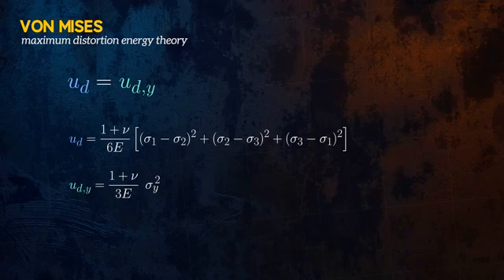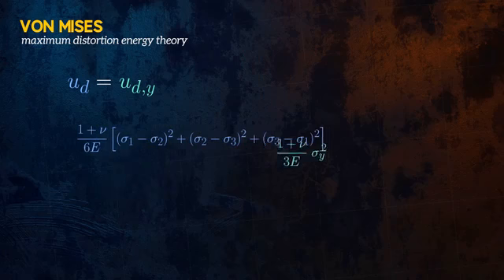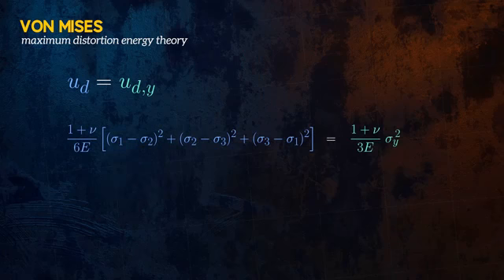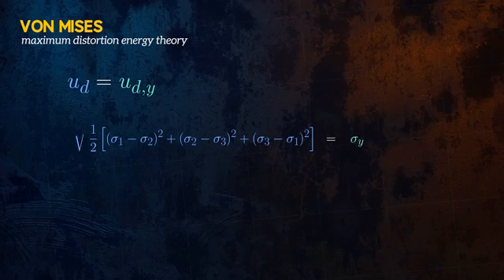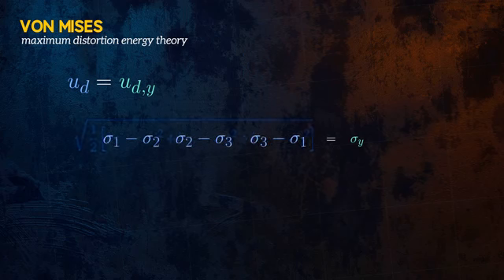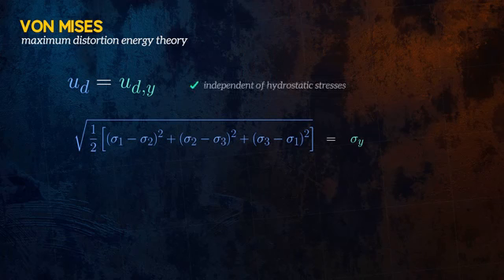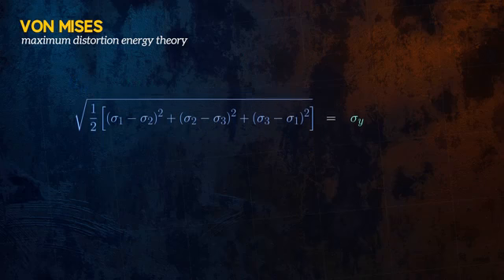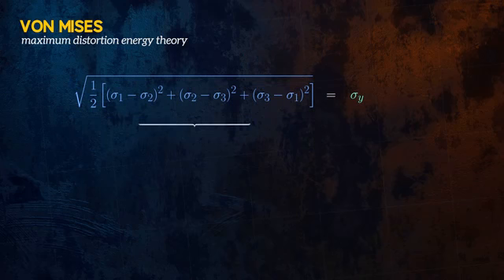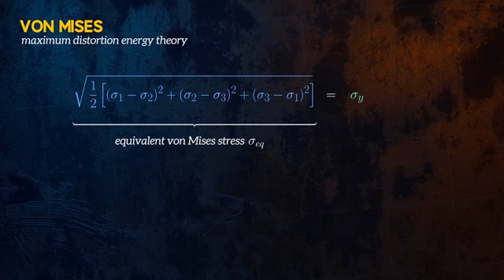And by equating the distortion energy at yielding with the general equation for a triaxial stress state and rearranging a bit, we get an equation that defines the von Mises failure criterion. Again, we can see that this theory considers the difference between principal stresses and so is independent of the hydrostatic stress. The term on the left is often called the equivalent von Mises stress. If it is larger than the yield strength of the material, yielding is predicted to have occurred.